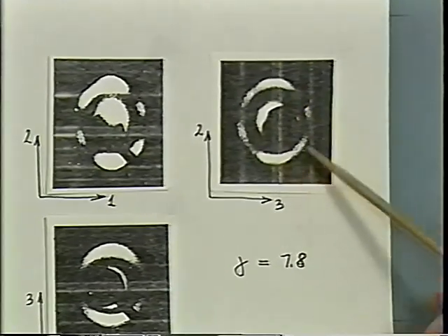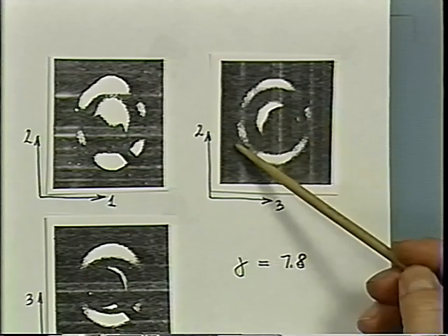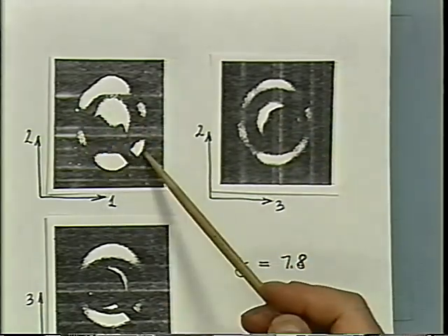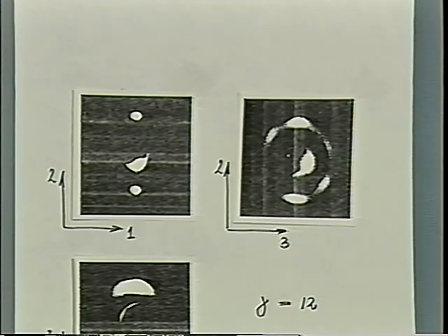So it would be interesting to pick up those intermediate structures, learn more about this intermediate order. And of course, we speculate where this comes from. I don't think it's really too important at this point. OK, so at about 3 shear units, 2.8, the sample starts to randomize in its order. And close to 8 shear units, we already have the hexagon coming up. We have some reflections coming in. Those reflections are getting weaker and weaker. And then after 12 shear units, you will see the new structure coming in.